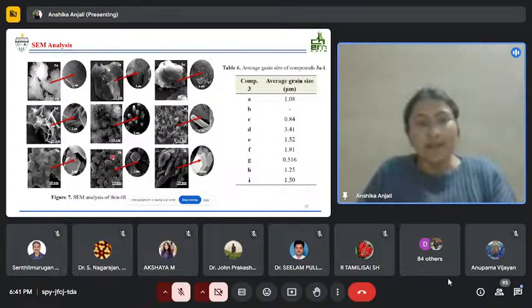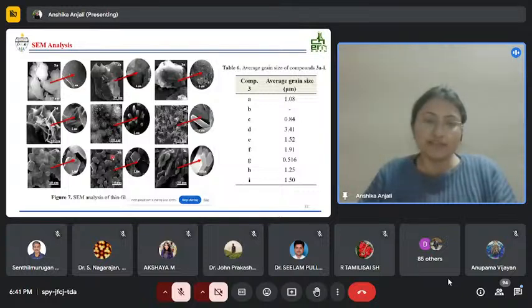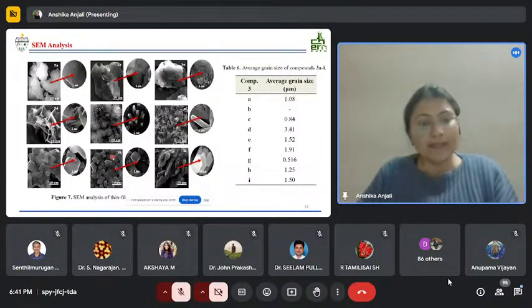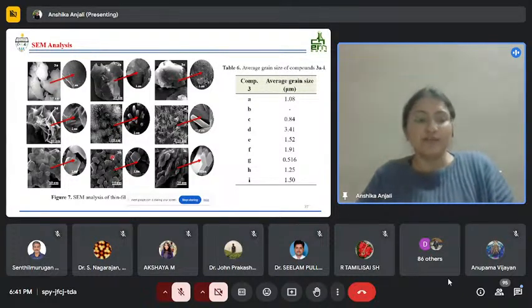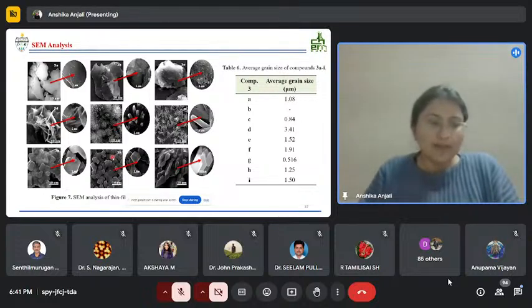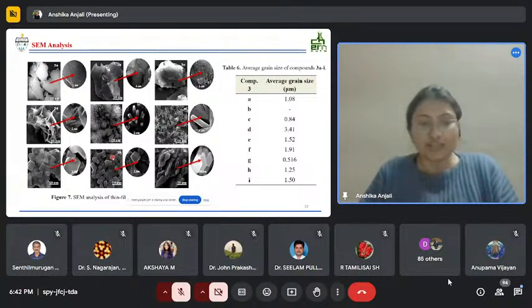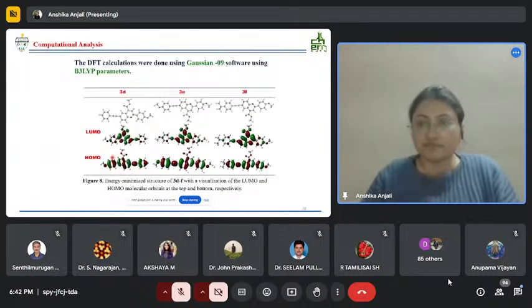And here for compounds 3A, 3B, and 3C, we have observed microbundles. Compounds 3D, 3E, and 3F, which have a 4-methoxyphenyl group at the second position, resulted in a flower-like morphology. And compounds 3G, 3H, and 3I with 4-fluorophenyl group at one terminal resulted in closely packed cuboids and hexagonal structures. So for these compounds, their average grain size values were also calculated.